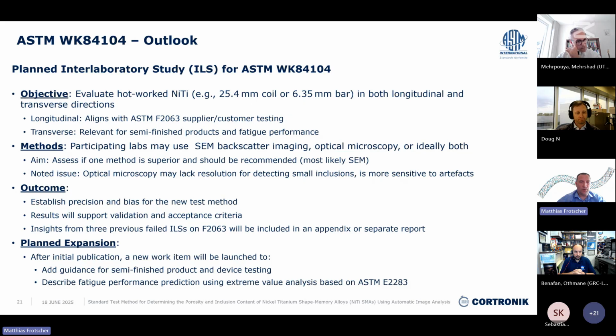So what do we want to expand the document to after initial publication? We will add guidance for testing and analyzing semi-finished products and devices. And we will also describe a procedure for how you can use the inclusion analysis to eventually perform predictions about the fatigue performance using a methodology known from the steel industry. So we are leveraging here a little bit from the decades-long experience in steels, and this is about extreme value analysis, a statistical method that can be applied to make fatigue predictions about service life.